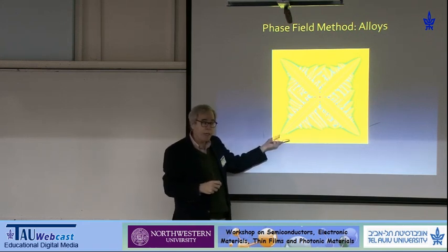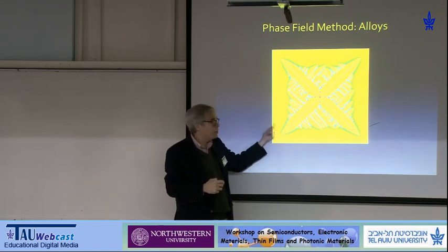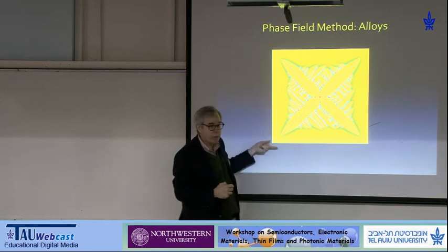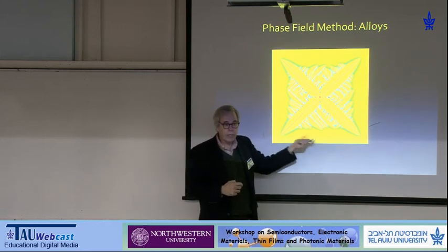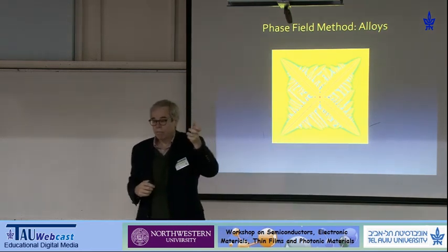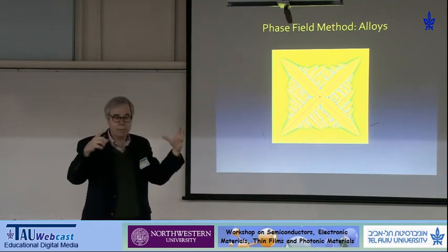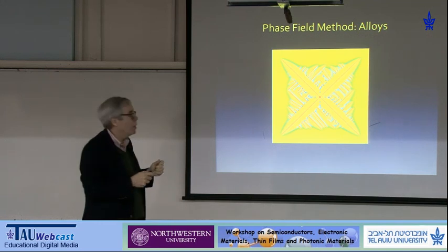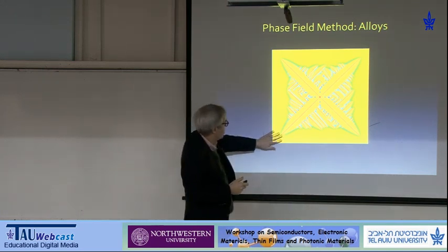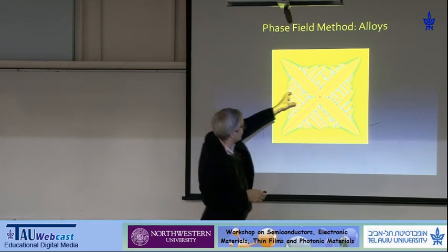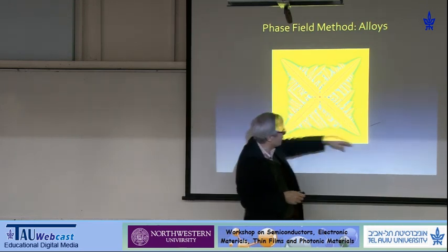Because what was happening here is that the anisotropy of the grid would introduce enough anisotropy in the interfacial energy that you get beautiful dendrites going along these directions. And as soon as they refined the grid, the secondary dendrite arms disappeared, and you got blobs. Okay, and so Jim and Bill were very much aware of that, which is why it's canted at a strange angle with respect to the computational box.